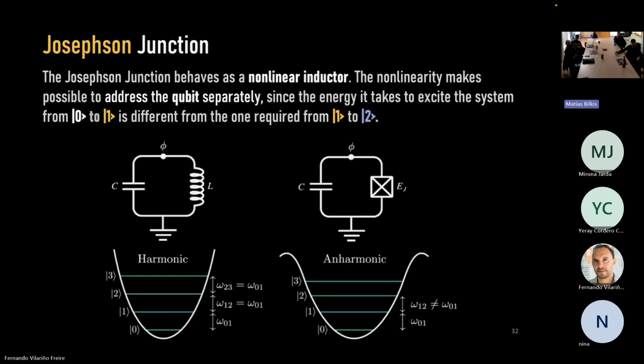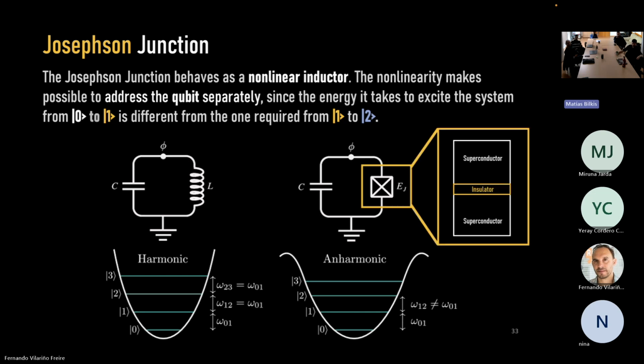In particular, the Josephson junction behaves like a nonlinear inductor. This means that if you have an LC circuit, you can replace the inductor with a Josephson junction, and you will introduce an anharmonicity, which is very important, because at this point you do not have the energies 0 and 1, 1 and 2, 2 and 3 all the same, but the 0 and 1 energy is different from the 1 and 2 energy. So then you can isolate the ground and first excited state, and finally you have a two-level system.